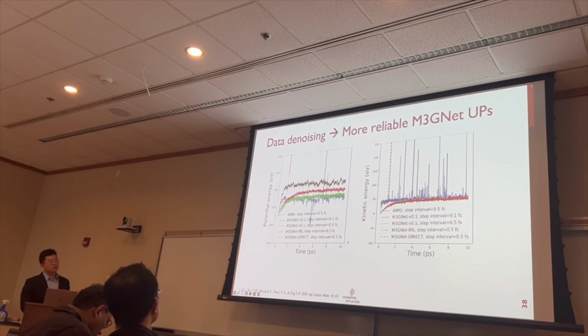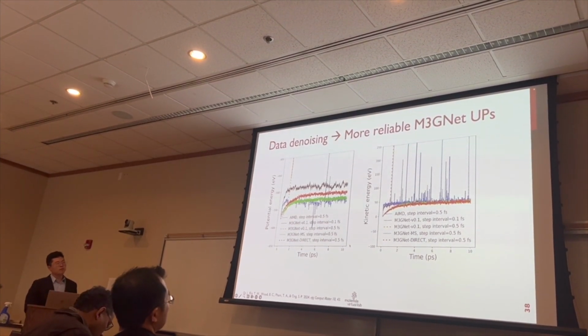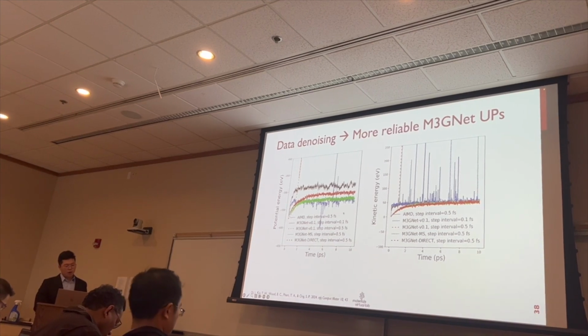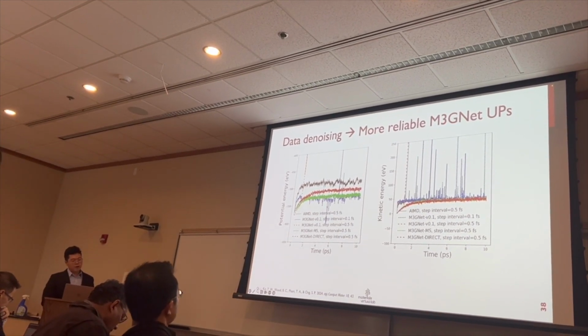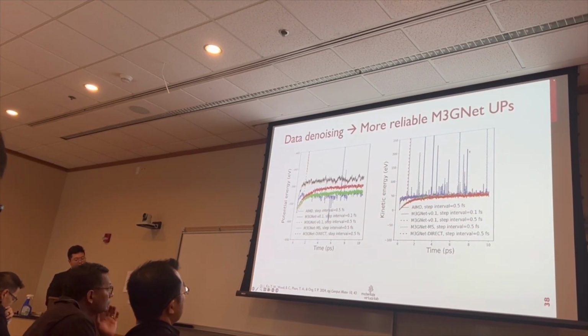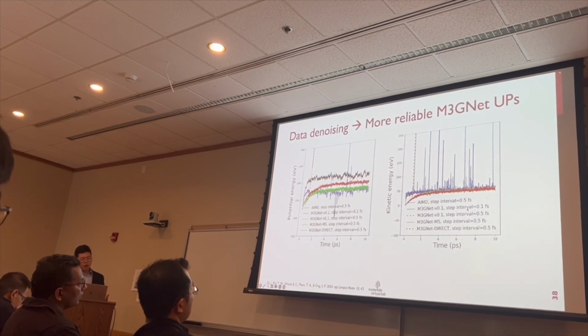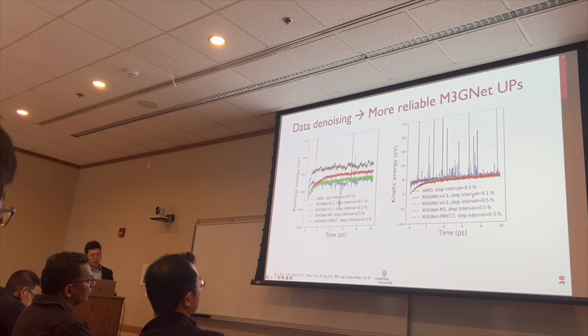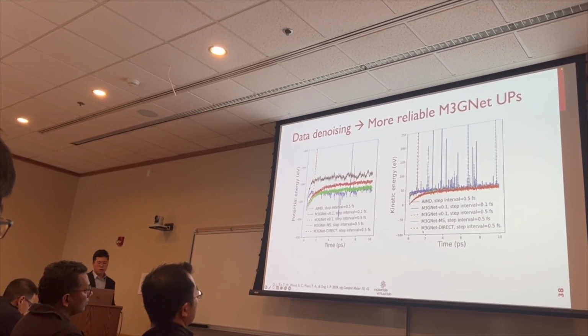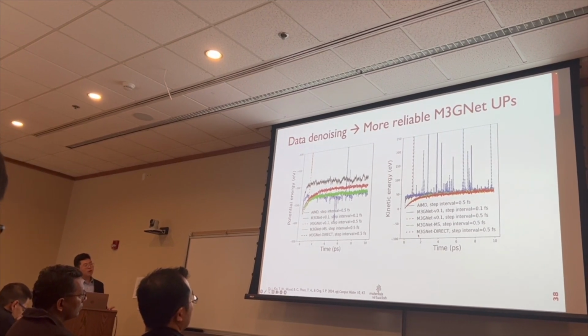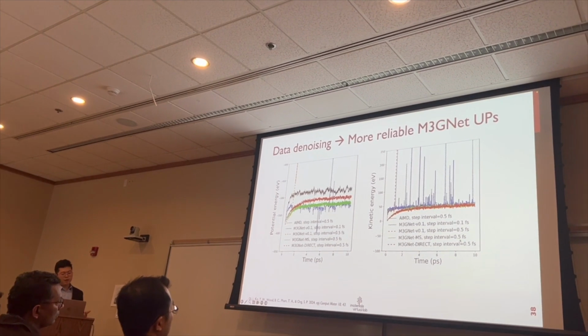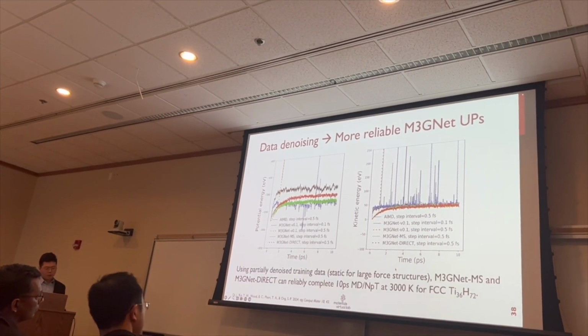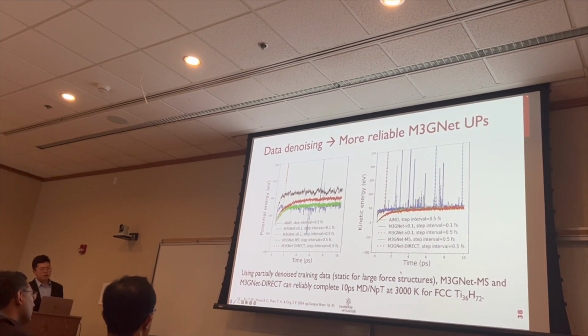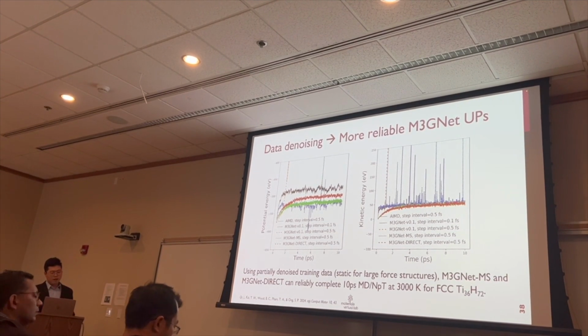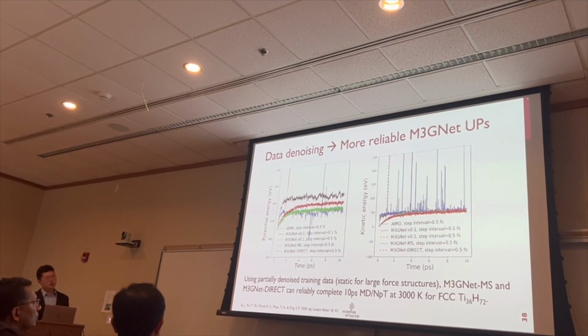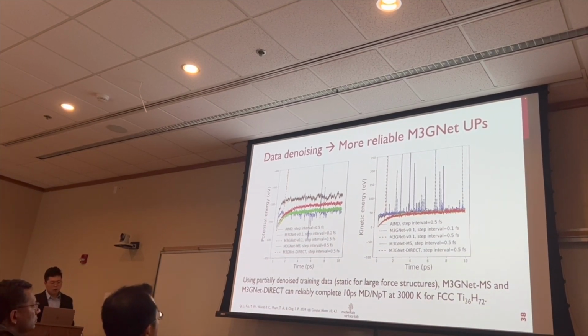In this case, we performed molecular dynamics simulation at 3000 Kelvin for titanium hydrogen. And you can see that the original M3GNet with the version 0.1 is not able to get a reasonable convergence of the simulation even with a very small step interval of 0.1 femtosecond, while our M3GNet manual sampling or direct sampling model can reliably complete the simulation with a reasonable time interval of 0.5 femtosecond. So this highlights that it's very crucial to reduce noise in the training set. And that's how we get a more reliable M3GNet direct data model with our method.